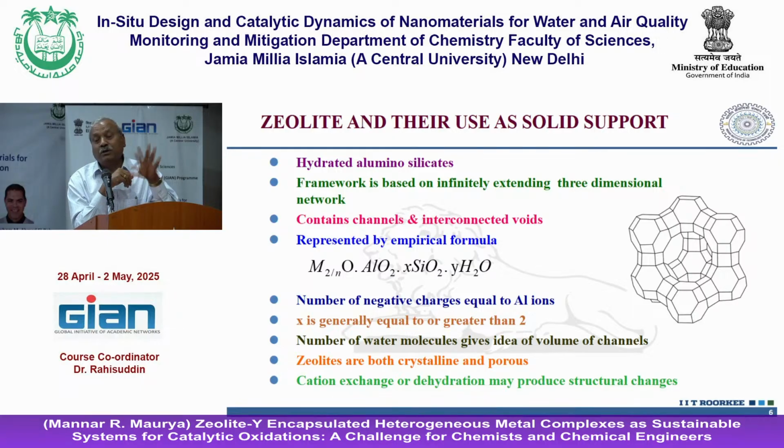Metal ion can also be replaced by hydrogen. When you take in the acid, the proton takes up. When you take in the base, the metal ion takes up, like sodium hydroxide. Sodium chloride, simply: if you have an H zeolite, treat it in water with sodium chloride, a saturated solution. Most of the hydrogen can be replaced by Na+, because the rest, balancing the charge, is taken up by the sodium ion.